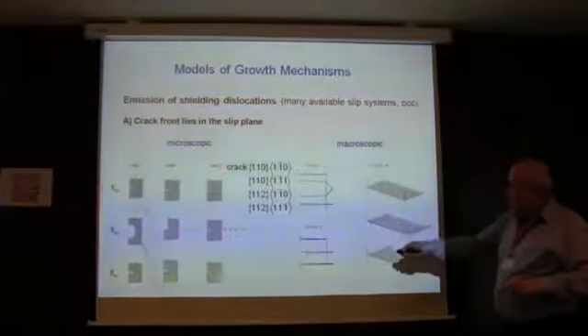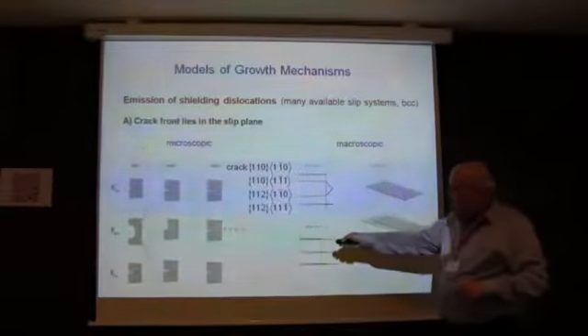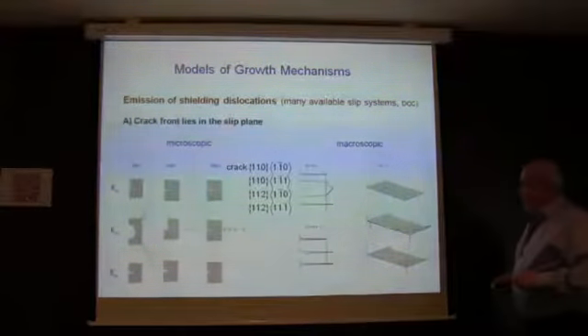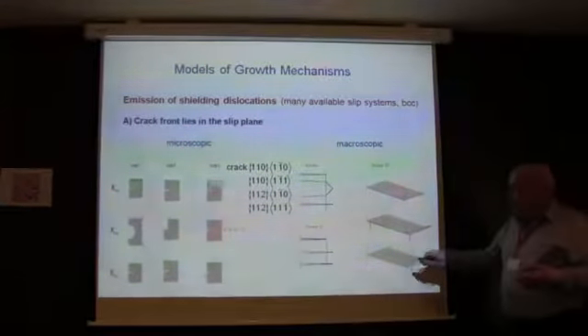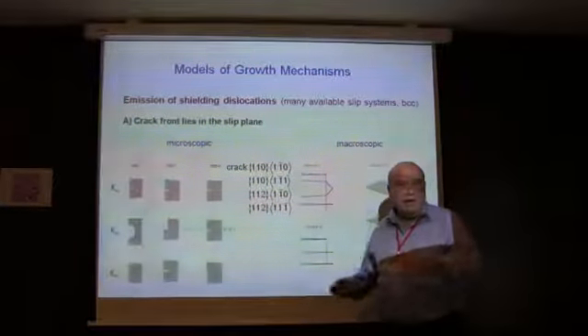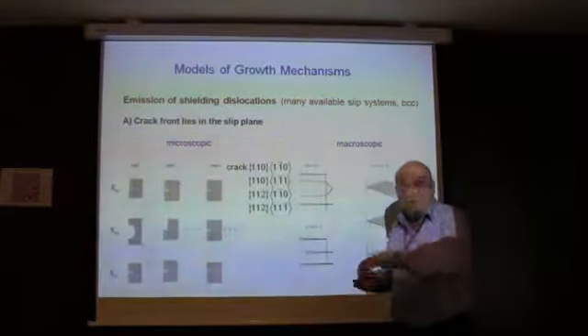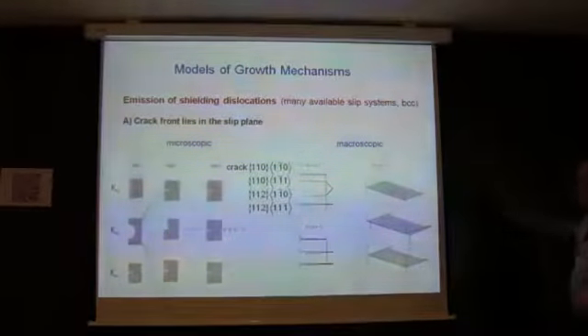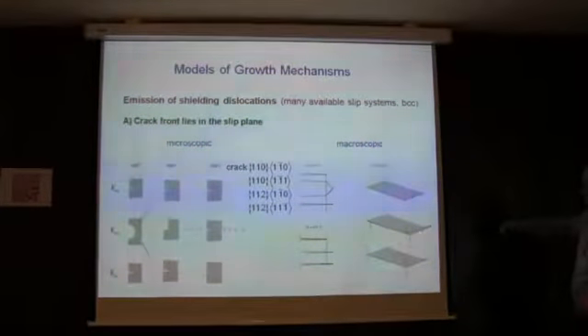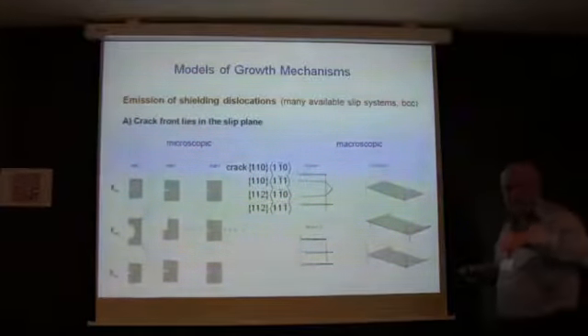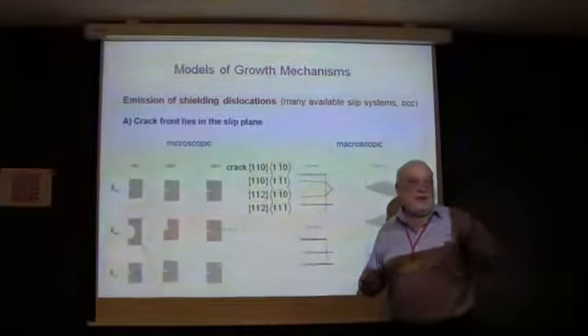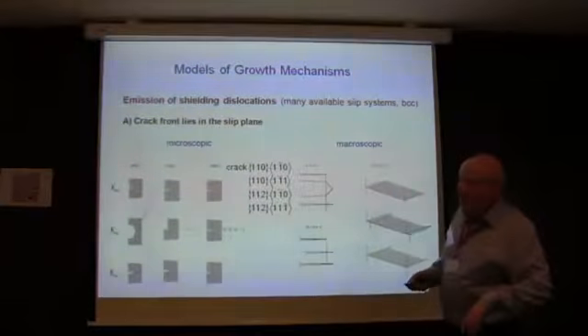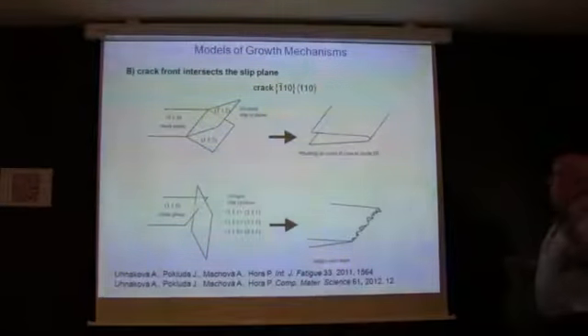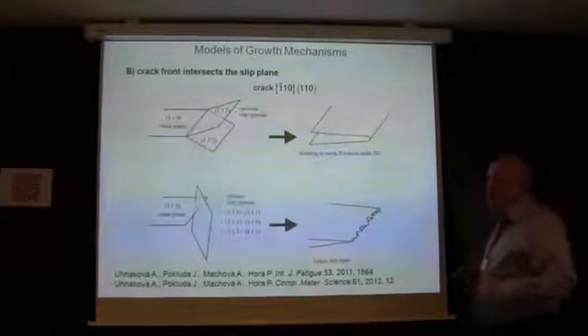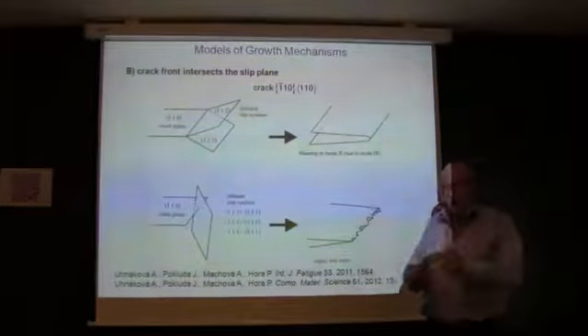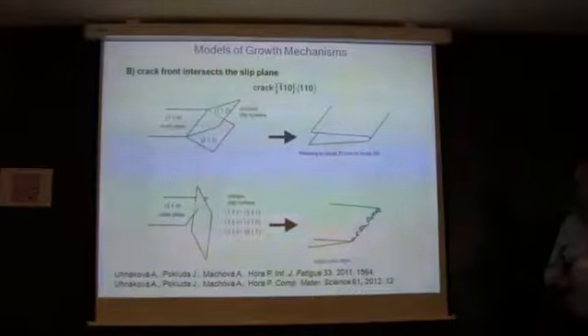But in mode 3, in this simple model, you actually emit screw dislocations, and they are not able to create any new surfaces ahead of the crack. This is a macroscopic model; they create them at the edges, not ahead of the crack. So this simple model doesn't explain mode 3 crack propagation at all. But this is really the simplest model. You can have, of course, many other cases of slip plane configuration, especially in polycrystalline material.